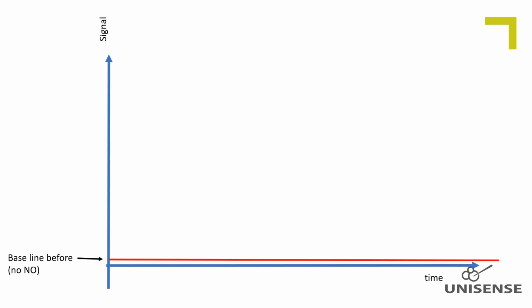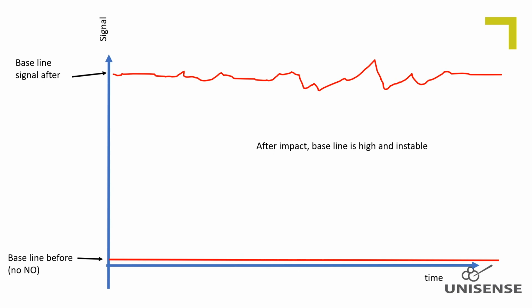A physical impact like a drop could also damage the glass insulation of the carbon wire connecting to the working electrode. This will typically result in an elevated and noisy baseline due to exposure of polarized carbon to the electrolyte. Chemical reactions taking place on the exposed carbon surface will create a current which will overlie the working electrode generated current. The size of the baseline increase will depend on the degree of damage to the carbon wire insulation. Such damage cannot be repaired.